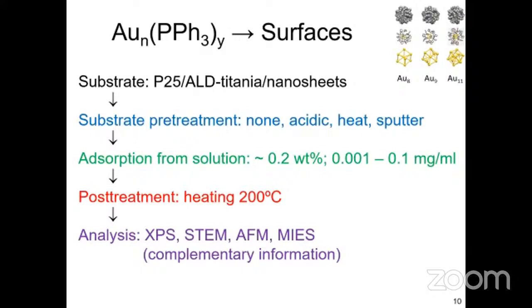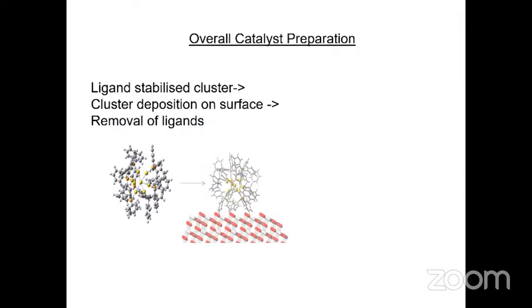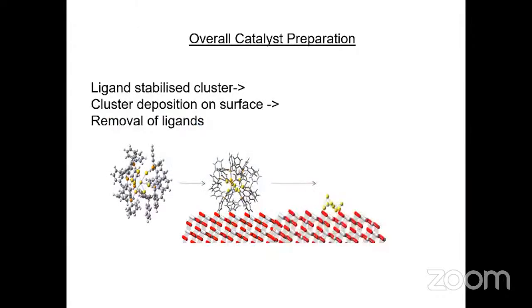Our main goal is to have this gold cluster at the end as a naked gold cluster, with the ligands removed and easy access, but without any aggregation of the cluster. This is as it is. We deposit them on the metal oxide and remove the ligands, and we aim to have this cluster as individual clusters. This is where the uniqueness of the catalytic activity of every precise nanocluster comes from.